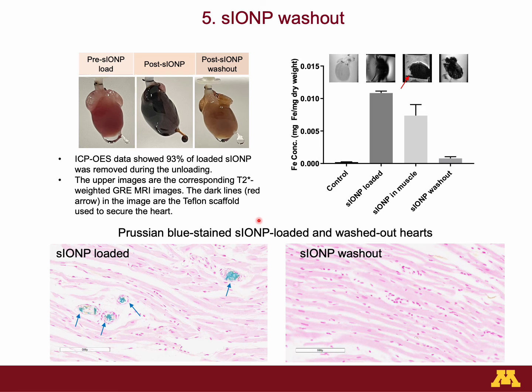The sIONP loaded and washed out hearts were processed for histology with Prussian blue staining to detect residual iron outside of the vasculature. The image showed blue staining, with pointed arrows indicating silica-coated iron oxide nanoparticles in the vasculature. There were no sIONPs in the parenchymal spaces of sIONP loaded and washed out hearts.